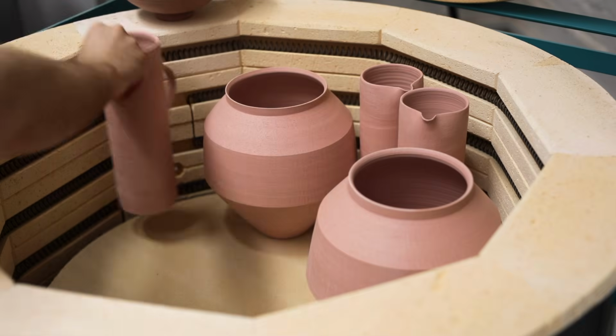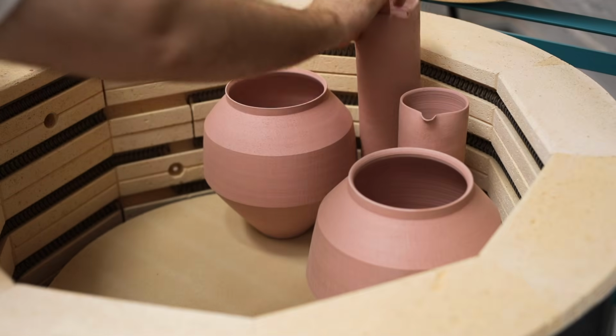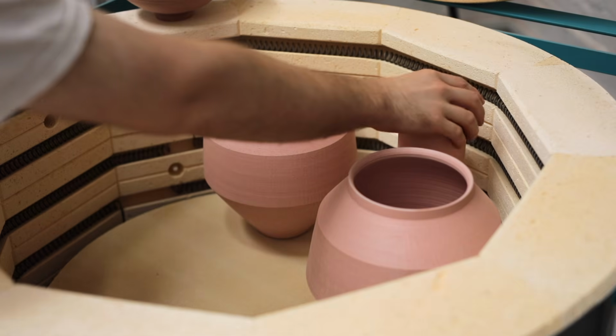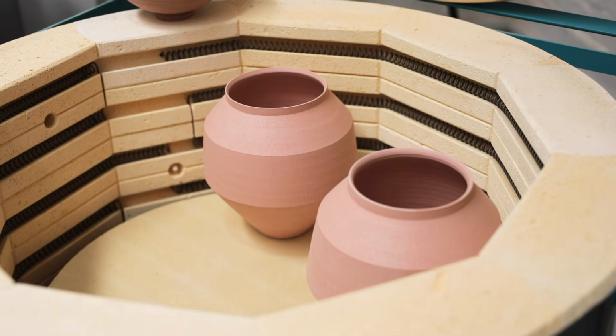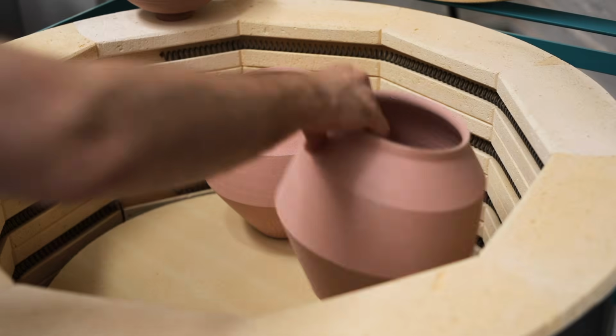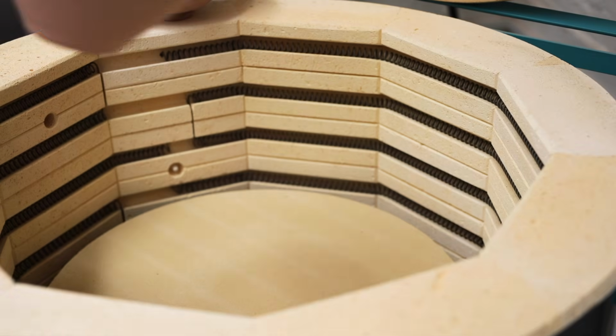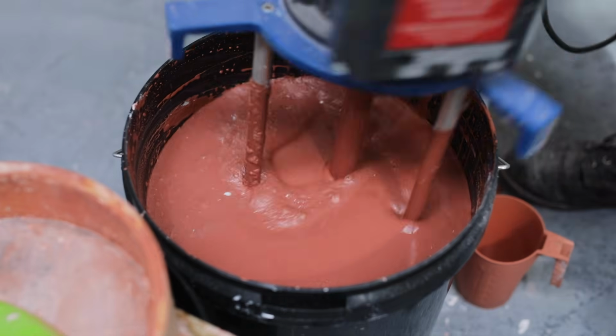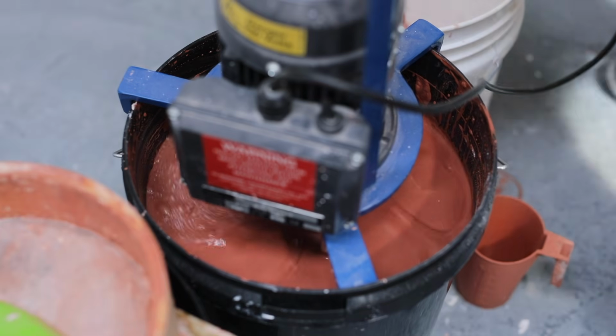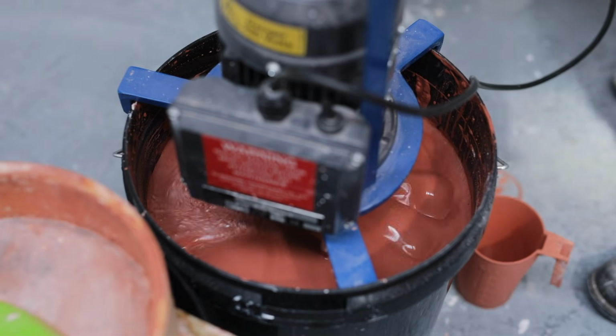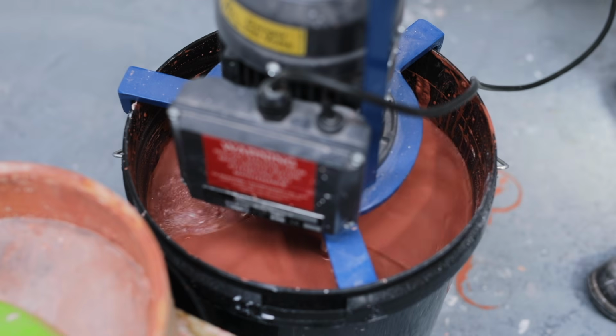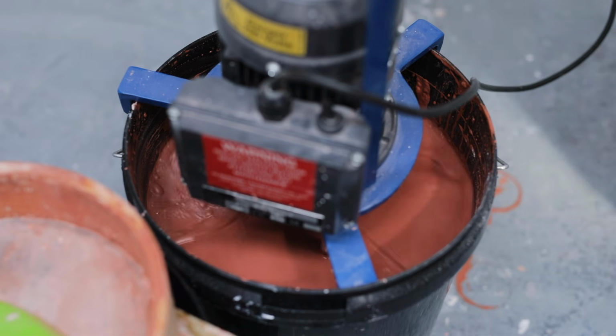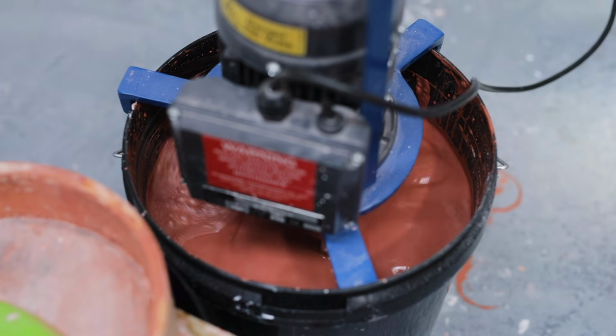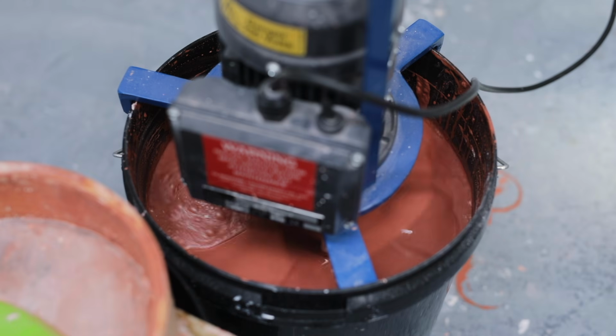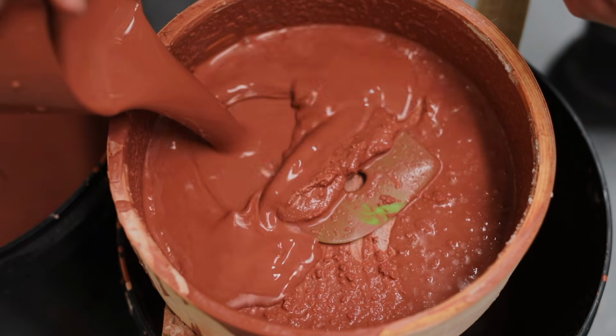Once the kiln is totally unpacked, the next task of the day is to mix up a new batch of glaze. I'm using a high feldspar crackle glaze, which contains a lot of potash feldspar, nepheline syenite, talc, some fluxes, a very small amount of synthetic bone ash, and for the colour, red iron oxide, which appears red now, but once fired, will turn into a deep dark green.